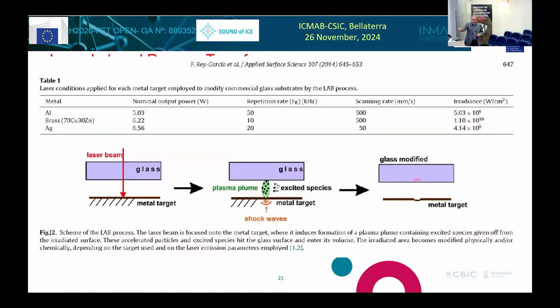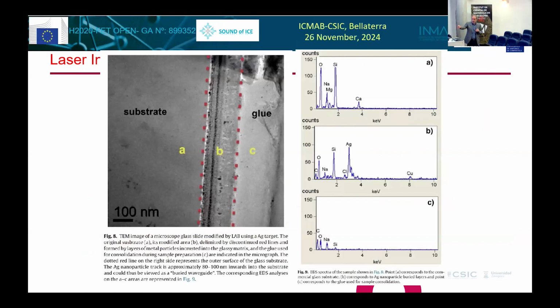You evaporate the metal target. It generates a plume. And if it is silver, then it generates a buried optical waveguide. So it's an optical waveguide which is induced by metal nanoparticles embedded in the glass, so they are protected from the ambient. This is where you can see how far they go in, almost 100 nanometers on the inside, but they're not on the surface. And this is because we use a very intense beam. If we use an intense beam, the kinetic energy of these nanoparticles is very high, and they just penetrate the glass. They're very hot, they penetrate the glass.